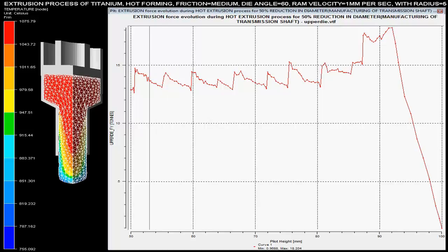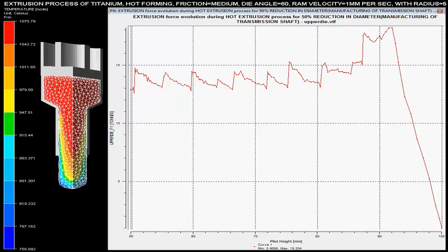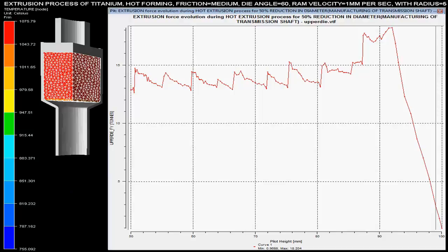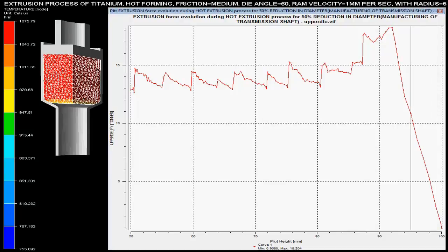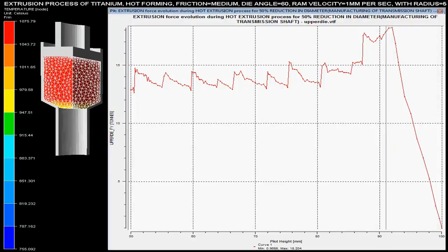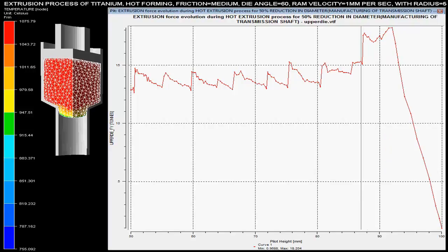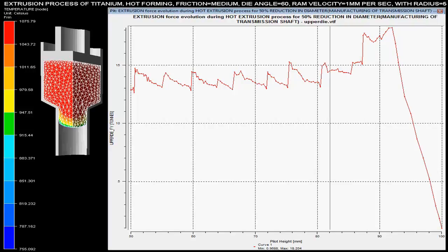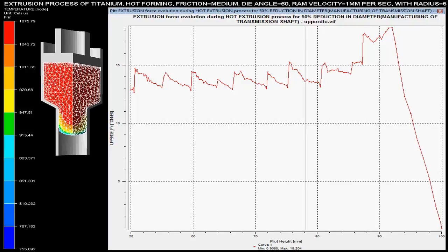As the pilot height reduces, the force required for the extrusion of the solid increases. Ram velocity is set as 1 mm per second with a radius of 5 mm. The die angle is specified as 60 degrees, and it is specified that there is medium friction during this hot extrusion process.